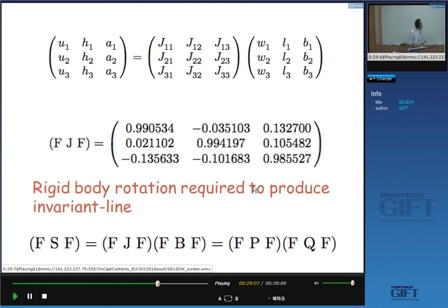It is just matrix calculation. So it is not that difficult to obtain the rotation matrix here, right? So far, so good. Now we have the rotation matrix, band deformation matrix, and lattice invariant shear. So it automatically gives you the matrix of the shape deformation. Now we can compare our calculation with experimental observation.